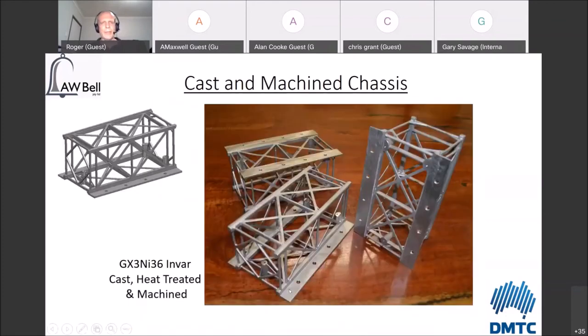And so then we end up with the cast parts. We clean them all up and take them and machine them. And you can see the first 3 satellite chassis that were cast here, all fully machined at our machine shop. We had to learn how to machine this material as well. It is very, very gummy, a lot like very soft 316 stainless. So you tend to form very gummy chips, and you have to be very careful while you're doing it, because of that fact.